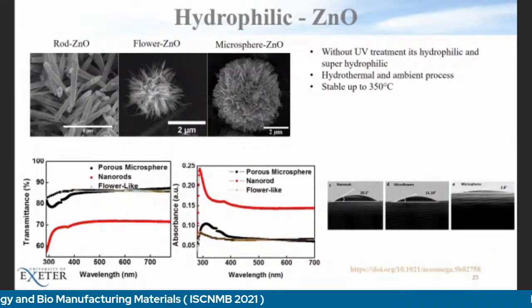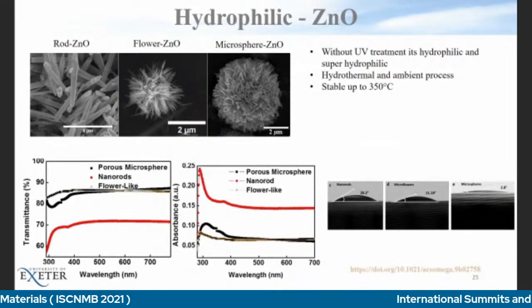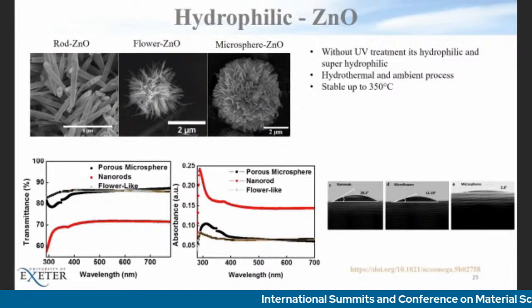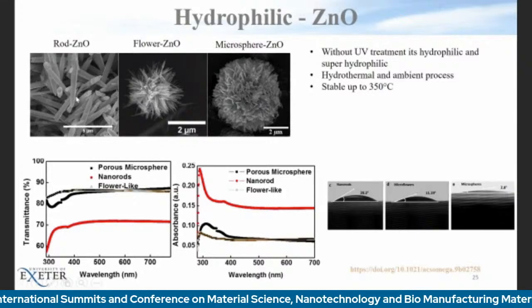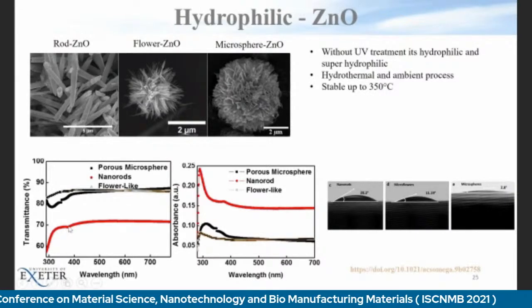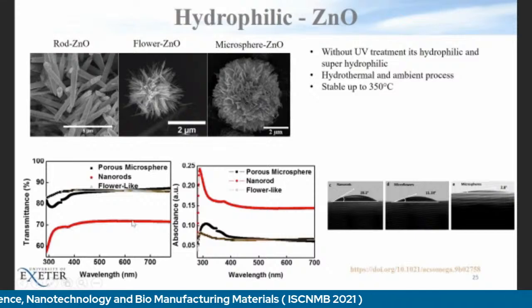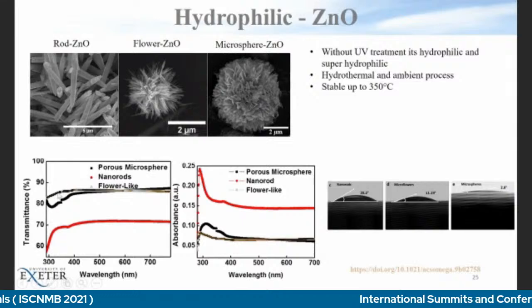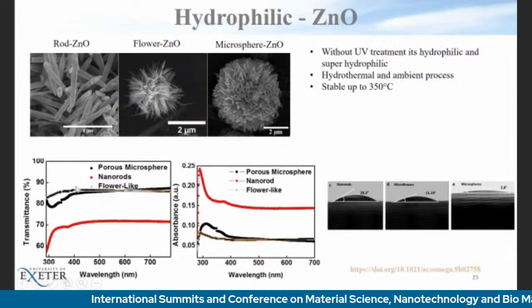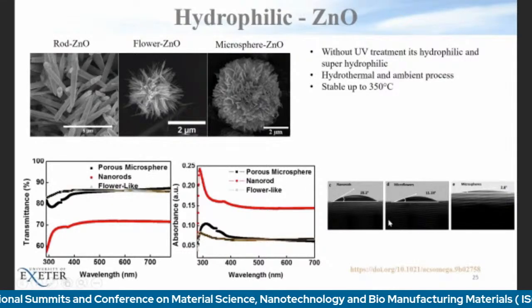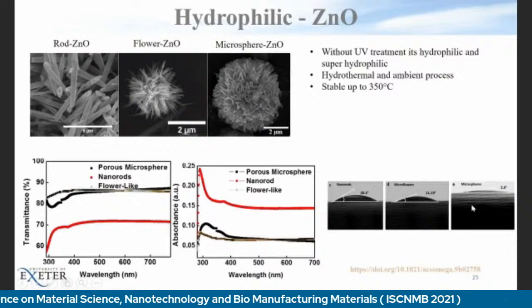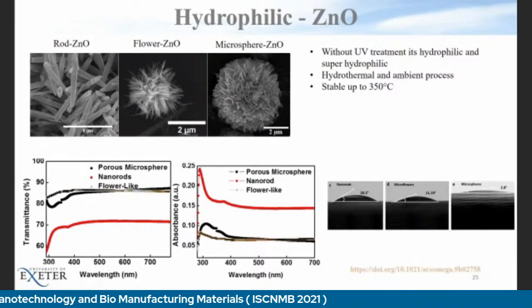Our first success came with the hydrophilic zinc oxide, where, as I already said, zinc oxide has a very intrinsic hydrophilic property, but the structure is very much the rod one. But we found that because of the nanorod structure, the transmission is very low. So that's the reason we tried to vary the morphology, and we actually got a very good success with the transmission, though it is not above 90%, which is required, but we reached close to 87 or 88%. And here you can see that we have also got the super hydrophilic property by just changing the morphology, not using any UV treatment. And this is our key success, and we have published this work.